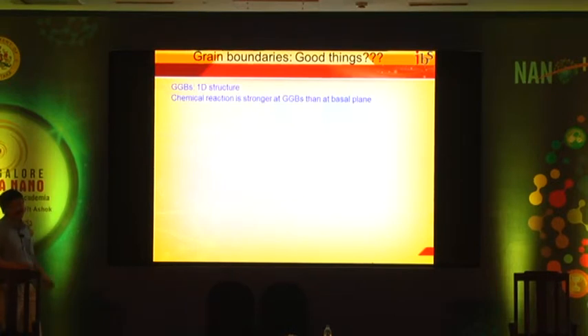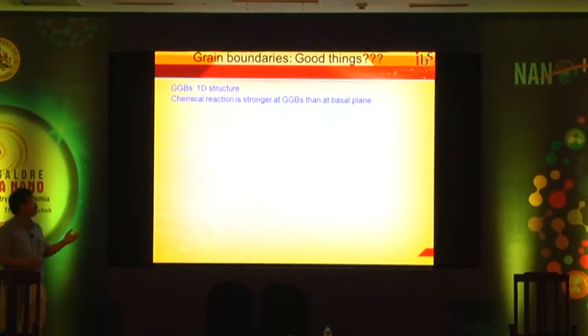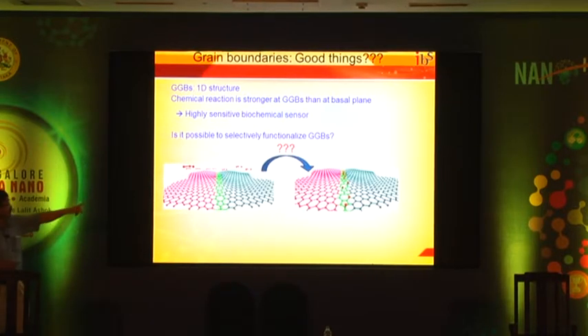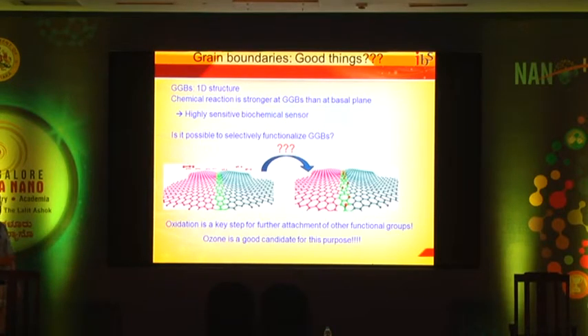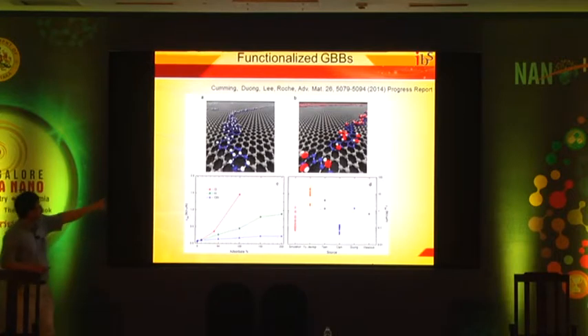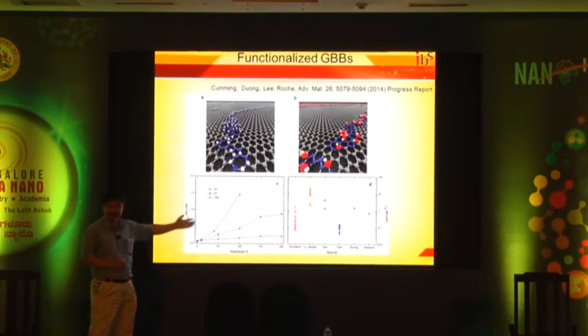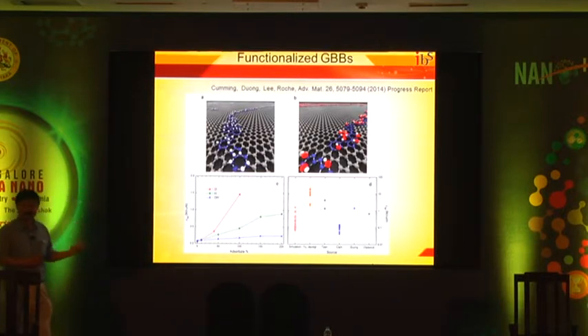Okay, so from an application point of view, is this grain boundary really the worst thing? We thought about this, and actually the grain boundary is very sensitive to environmental gases, which can be used as some kind of gas sensor. You can manipulate this grain boundary with many different chemicals that show different electrical conductivity reactions. So at some point, if you'd like to use it, this will certainly be an advantage. This is one good example. You can decorate this grain boundary with different radicals, different amounts. You can see there are systematic changes. So you can use these characteristics as a sort of application for sensors.